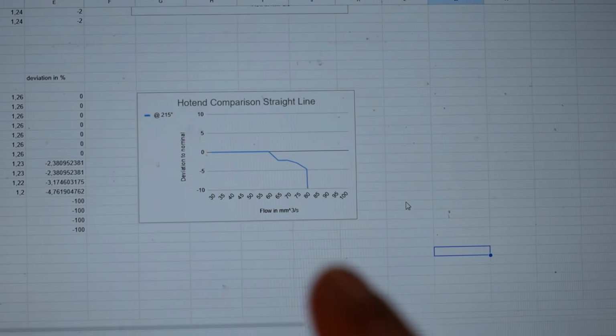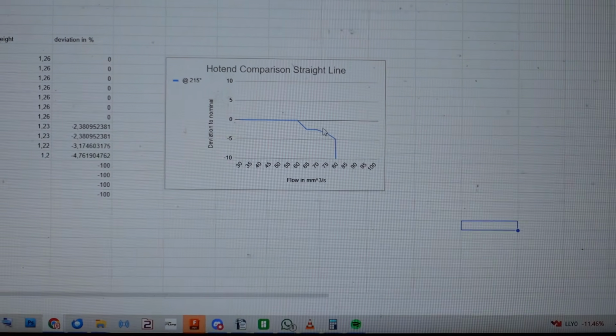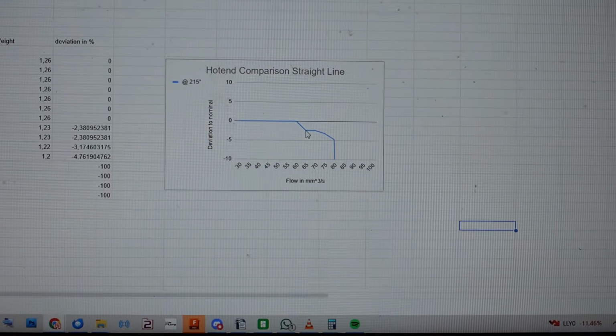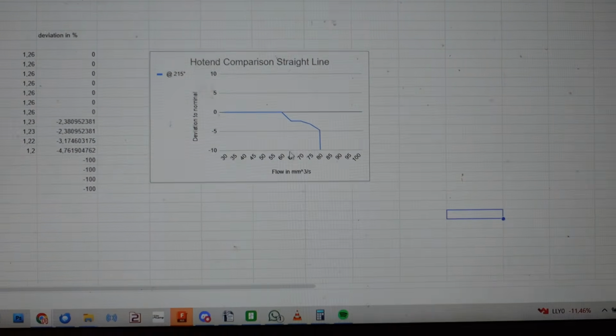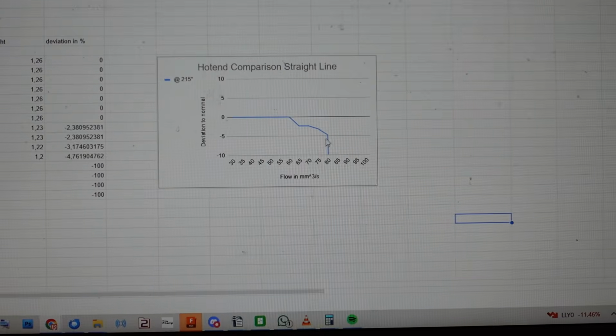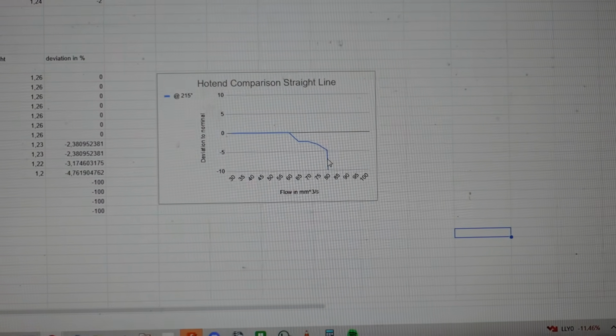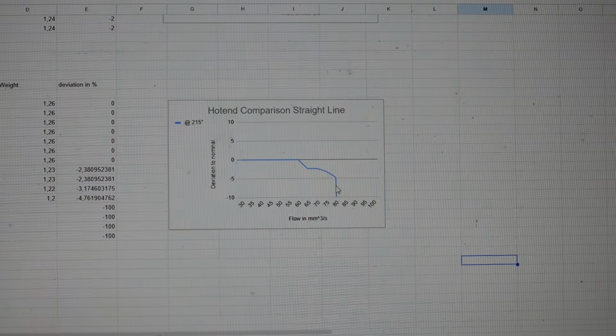So I'll put these on the screen later on, but you can see here I could measure the first deviation of 2% at around 60 cubes. Then it started to go down, and after 80, yeah, the system isn't capable to do that. So the thing is, take these numbers with a grain of salt. This isn't comparable to any other 3D printer or Hotend or something. I just care about relative measurements here.